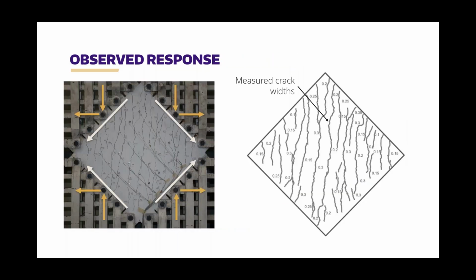Here's what you see, just a typical panel test. You can see we're subjecting this to pure shear. So you have to push with one set of actuators and pull with the other. And that produces that diagonal shear stress there. Because of that, you can see the cracks are oriented mostly vertical, which is great. That's exactly what we want to see. Eventually, this localizes and you get one big crack all the way through the middle. But you can see there's a crack mapping that's going on here, and so we digitize that. So we'll have these sorts of plots to show.